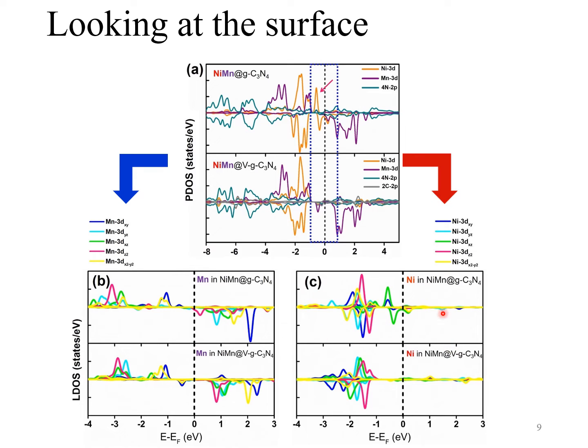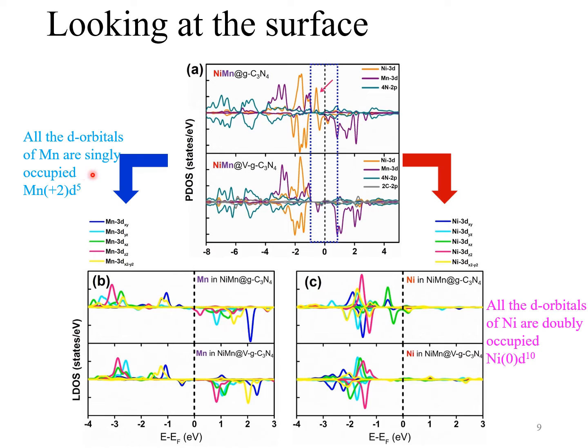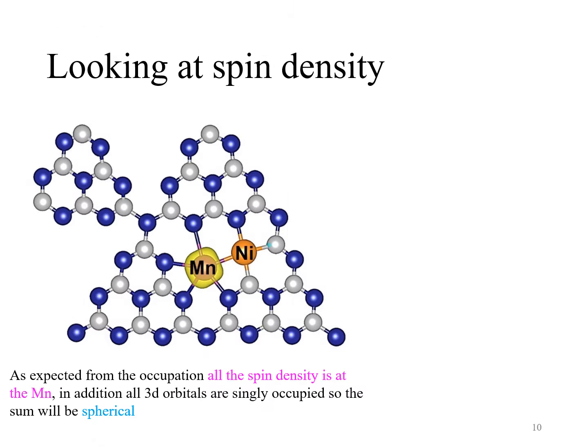Looking at this nickel for both pristine and vacancy graphitic carbon nitride, we can see all the d orbitals are occupied, signifying we have nickel, zero oxidation state, D10 occupation. On the other hand, when you look at the manganese side, we can see only the alpha or the up spin being occupied and beta being mainly unoccupied. Therefore, manganese will take +2 oxidation state with D5 occupation. And if we look at the spin density, as expected, all the up-spin contributions are at the manganese. And since all 5 d orbitals are occupied, the sum is spherical.